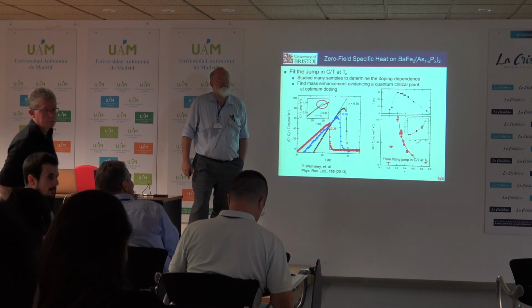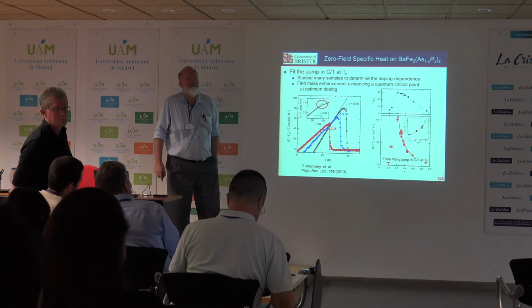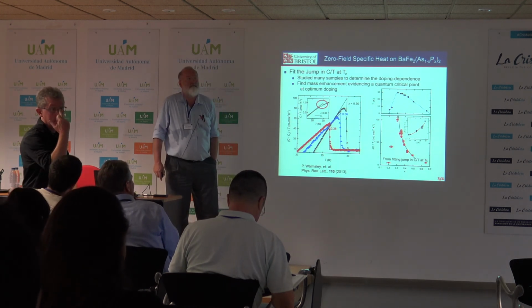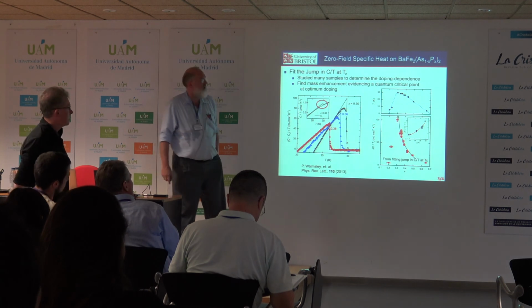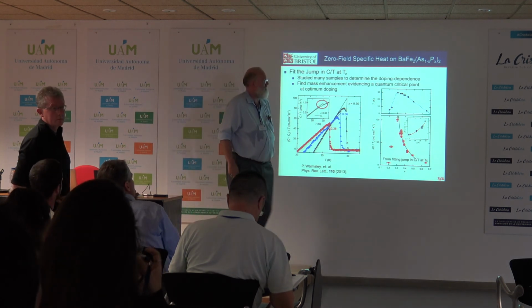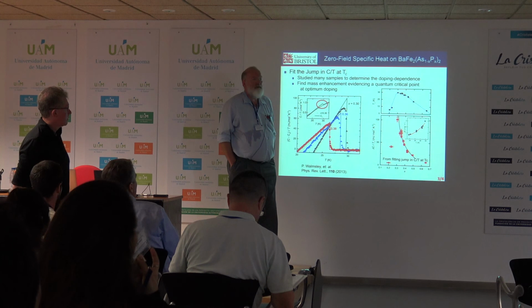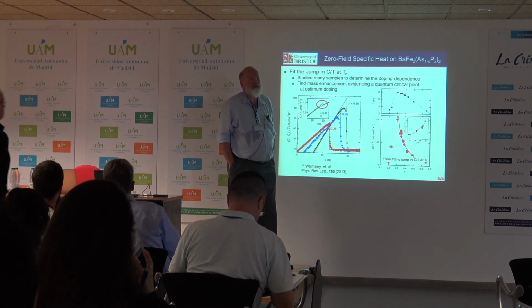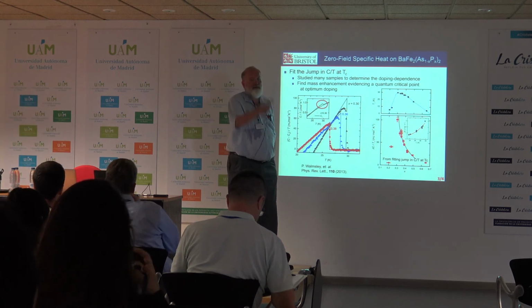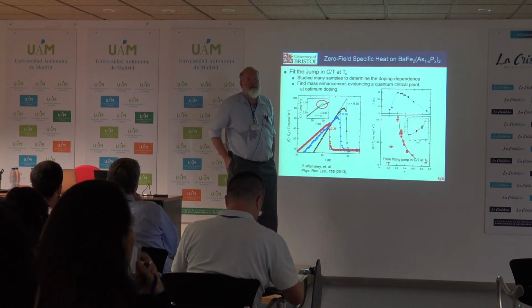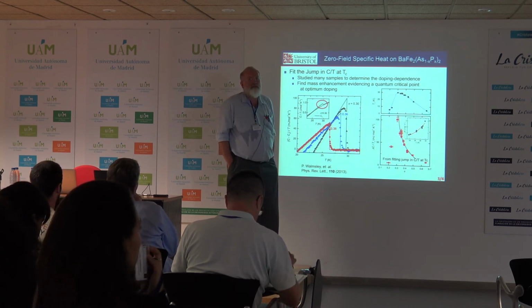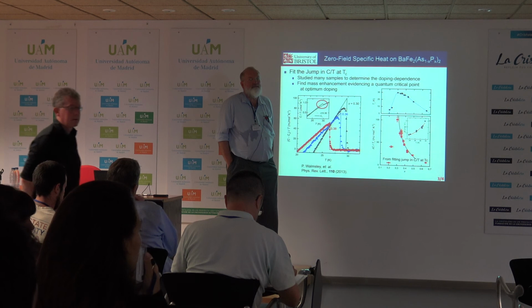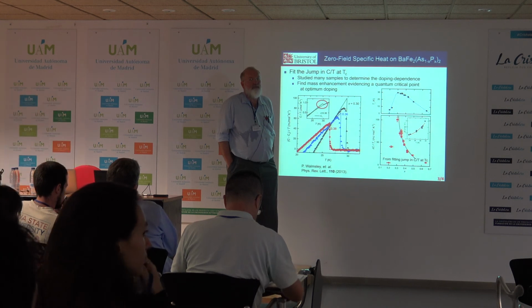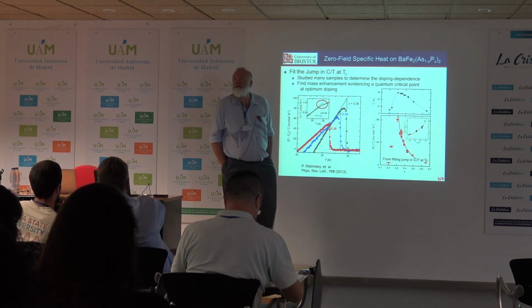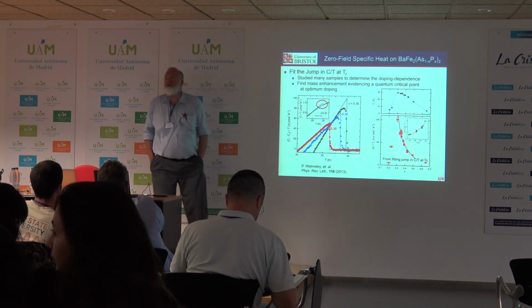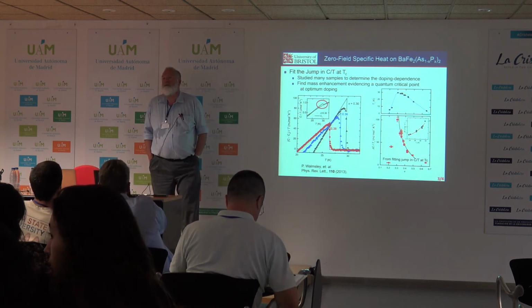The assumption in the analysis is that it's not strong coupling, and the main reason for that is that you see that TC doesn't change actually over that range of doping. And you link it to superfluid density, as I recall. Well, no, the interpretation of that jump is exactly in mass divergence. Right. That's it.